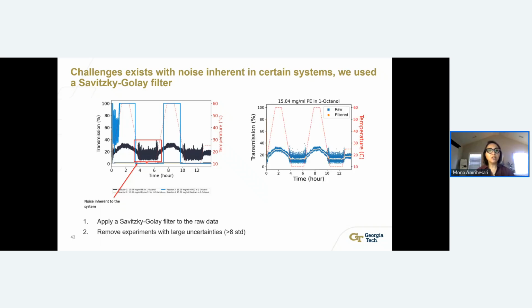We used a Savitzky-Golay filter in this case. We filtered data every 2 minutes, 3 minutes to get the signal, but avoid a lot of fluctuation in between. The reason for that is that Crystal 16 provides a very data-rich system. Every second you have a data point of the raw data. Going through this raw data of more than 60,000 data points for the same experiments, we didn't lose any kinetic insights, but we filtered the data in a way to increase the signal to noise ratio.